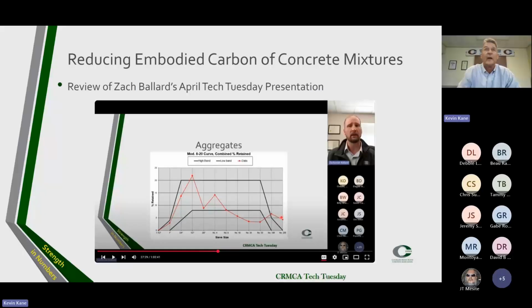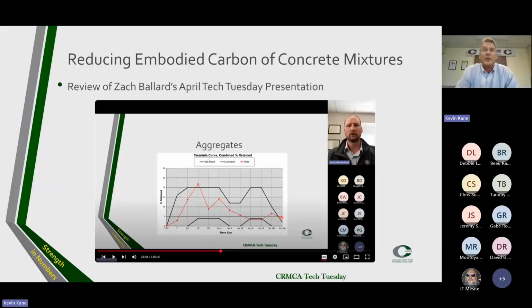Same thing with this tarantula curve that they developed. Tyler Ley down at Oklahoma State University developed this tarantula curve, and it's very good. It's very effective. But you're going to need an intermediate aggregate, if not two intermediate aggregates, to find your way into this tarantula curve. But when you do, boy, you can really optimize your aggregate grading and reduce your cementitious content.